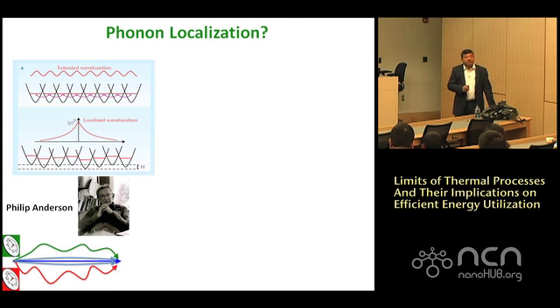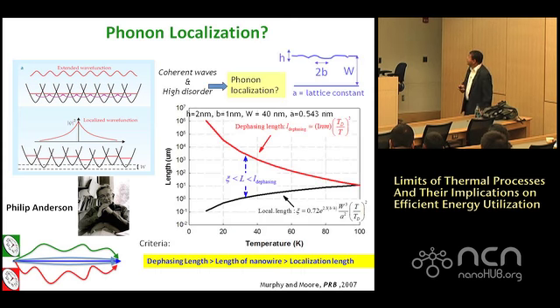It's worth a shot. And this will only happen when the wave does not dephase. That means you need a material which is crystalline, and you need the mean free paths, the coherence lengths, to be long, because that's how you get destructive interference. So it would rather happen in silicon and diamond than in bismuth telluride, which is a completely different way of looking at things. So we did some theory, and this is my colleague in the physics department at Berkeley, Joel Moore, and his student, Patrick Murphy. They said, okay, what are the different length scales involved in this?